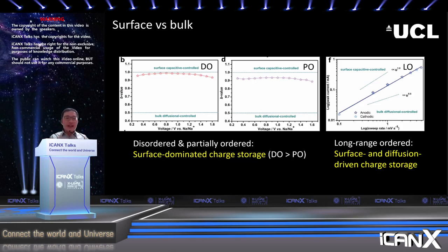The advantage of that shift is that the surface storage process has much less resistance compared to the bulk storage process. It's easier to imagine that if you have ions moving around on the surface of the material, it will have wide open space to move around. But when you think of the ions diffusing around inside the bulk material, then there's very limited space and sites where the ions can be accommodated.